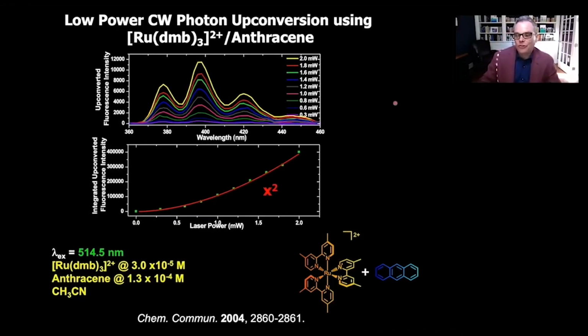And then more into the technical details. So if you excite out here in the green, turning your detector anti-Stokes, you can see as a function of incident continuous wave laser power, you generate anthracene fluorescence in this mixture. And that follows very beautifully the quadratic incident light power dependence. And it's quadratic for a simple reason. You have to have two acceptors sensitized in order to generate this fluorescence. So that's where the square comes from in the rate law. And it's as simple as that.